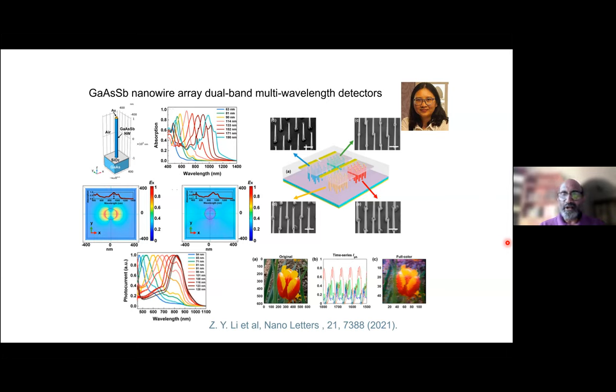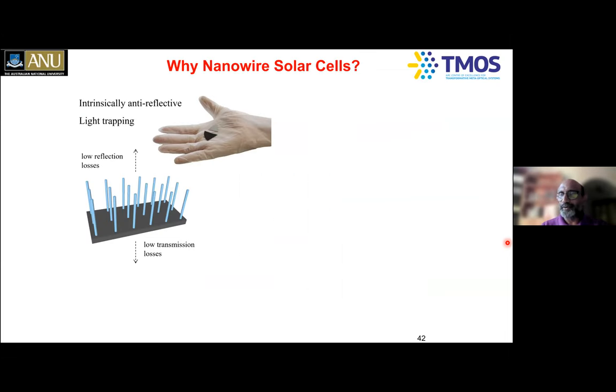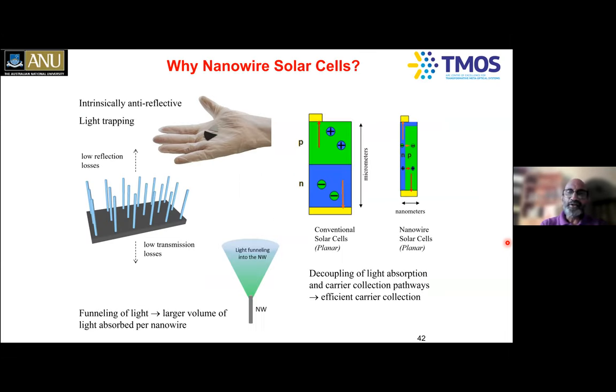Now let me move towards nanowire solar cells. Solar cells, all of us have studied about solar cells. So really, you talk about a thin film solar cell, you make a PN junction, and then you make it thick enough to absorb all the sunlight, you make the contacts at the top and the bottom. So that means you can collect the current, for example. Then you say the solar cell is about 20% efficient, and 80% of the carriers have been lost to defects or impurities or surfaces.